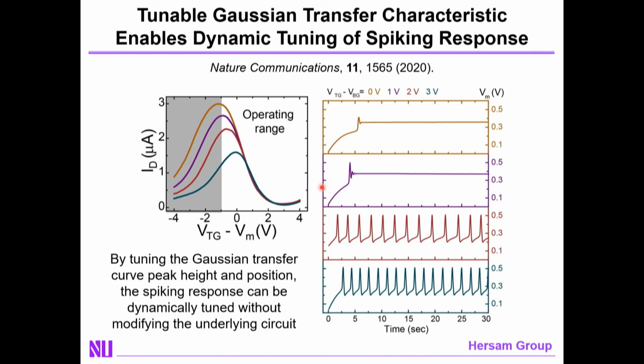To illustrate that, what I'm going to show you is a few examples where all we're doing is tuning the peak position of the Gaussian response. Depending upon where the operating voltage is compared to the peak of the Gaussian, you'll either see single spiking behavior or multiple spiking behavior where the time scale or spacing in time between spikes is tuned based upon how far you move down on the positive transconductance side of your anti-ambipolar response, a high degree of tunability and reconfigurability.